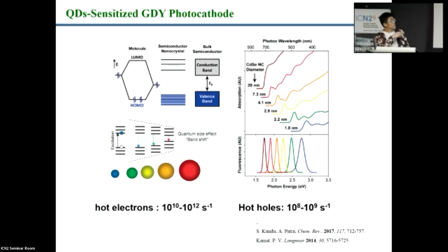We didn't try that, because here we assembled the quantum dots. We use 4-mercaptopyridine to functionalize these quantum dots, and the 4-mercaptopyridine has pi-pi interactions with the graphene. So we just need to put our graphene in this solution, and it can absorb by pi stacking.